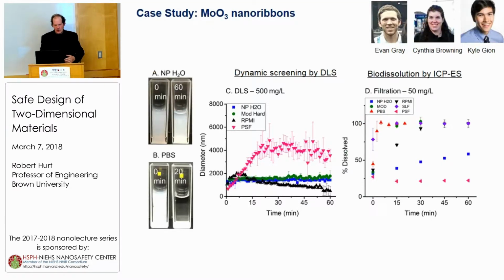And we took these materials and worked with them. This is Evan Gray, a postdoc in my lab, and Cynthia Browning is a postdoc in Agnes's lab. And we found out they were stable in nanopure water. They formed this cloudy, sort of milky suspension. But in some other media, like phosphate buffered saline, they seemed to clear in a pretty short time. And we did a bunch of DLS screening and eventually did this ICP measurement. Incubate the nanoribbons in the medium of choice. We remove the solids by centrifugal ultrafiltration, and we assay the supernatant for, in this case, molybdenum as a marker for the presence of dissolved molybdenum trioxide.